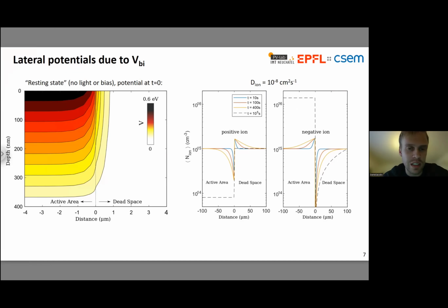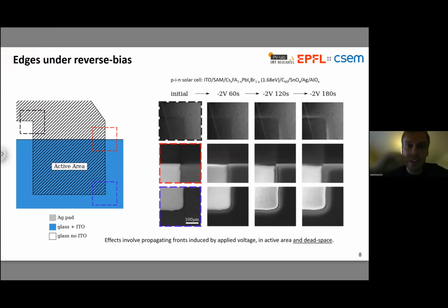So that's, I think, a fairly good indication that this effect stands a chance of being relevant, especially now that we're testing devices not over minutes and hours, but hundreds, thousands, if we're lucky, tens of thousands of hours. There's certainly a chance for this type of migration to be relevant. So if we were justified in the early days in ignoring these effects because we were only testing devices for a couple of minutes or an hour, that's not the case anymore now that we're running tests for longer periods of time.